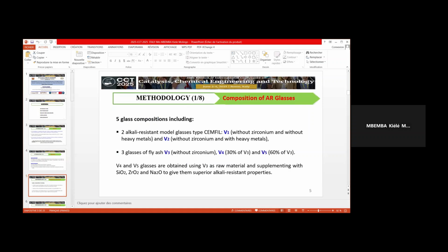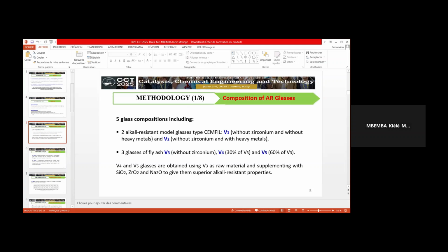So for the methodology we used, we first prepared 5 glass compositions, including 2 alkali-resistant model glasses of the CEMFIL type, namely V1, a glass without zirconium and without heavy metals, and V2, a glass without zirconium but with heavy metals, and 3 fly ash glasses: V3, which is a glass without zirconium and without heavy metals, and V4 and V5, which are obtained using V3 as a raw material, 30% for V4 and 60% for V5, and supplementing with silicon oxide, zirconium oxide, and sodium oxide to give them superior alkali-resistant properties.